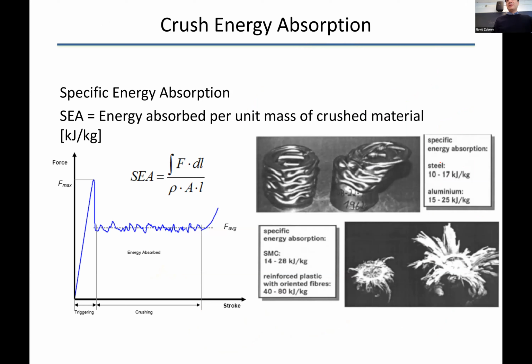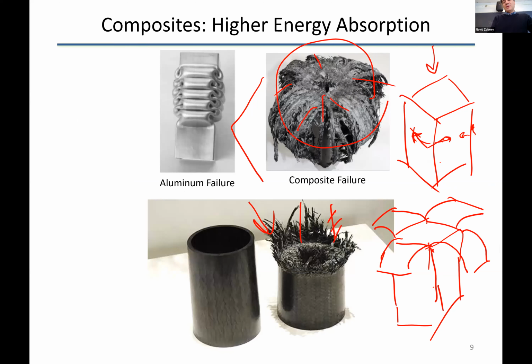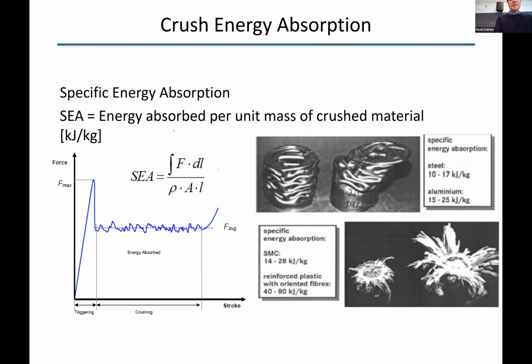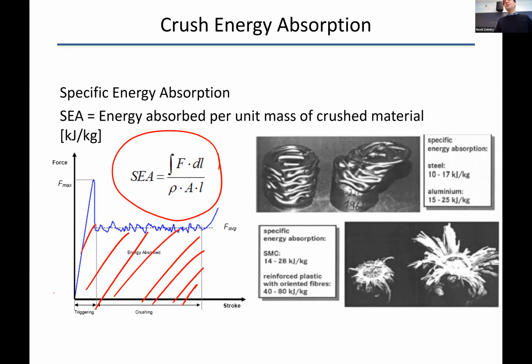So the main thing that we measure, it's a very messy process, as you can see. I mean, how do you measure this? When I was a PhD student, we had to simulate this, and it's a nightmare to simulate something like this, right? So there is one parameter that you look for in the performance of any component, and that is called specific energy absorption. You do a test, you plot force versus displacement, and then the area below the curve becomes how much energy was absorbed, and then you divide it by the mass that was crushed. And so it's energy absorbed per unit mass of crushed material, kilojoules per kilogram, for example.